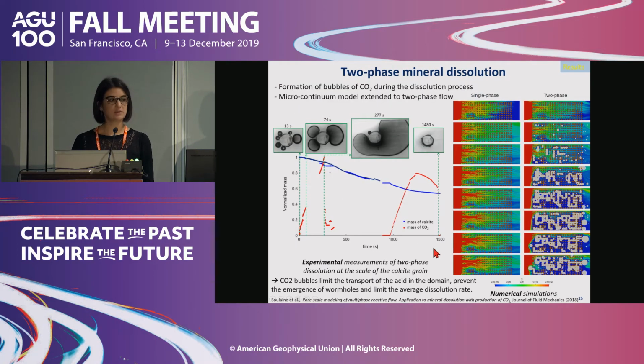So then we extended this work to two-phase dissolution. That is, when the CO2 that is produced during the reaction is not directly dissolved in the water, but also produces CO2 bubbles. This is the same experimental setup, but now we have the production of gas CO2. During the experiment, we see that at the beginning we have small bubbles of CO2 that will grow, they will coalesce, and at some point they will form a large bubble of CO2 that will detach from the calcite.